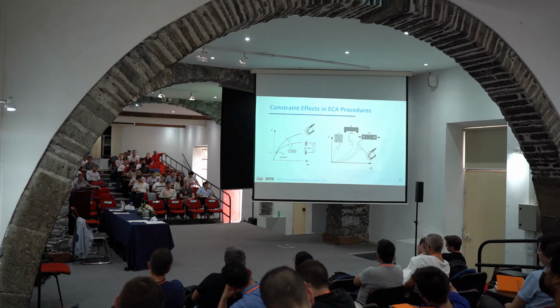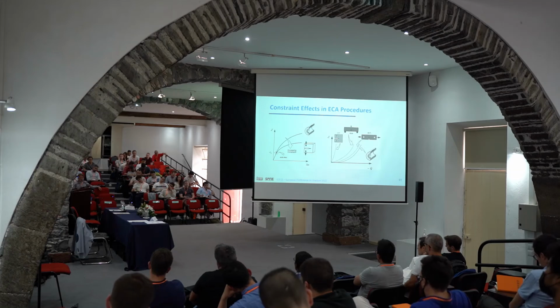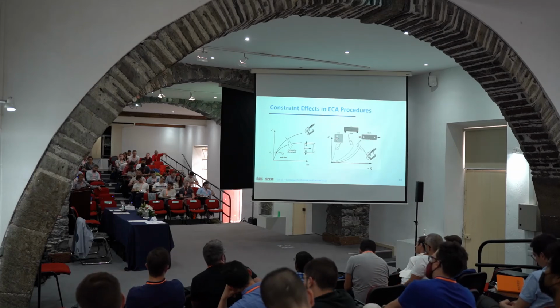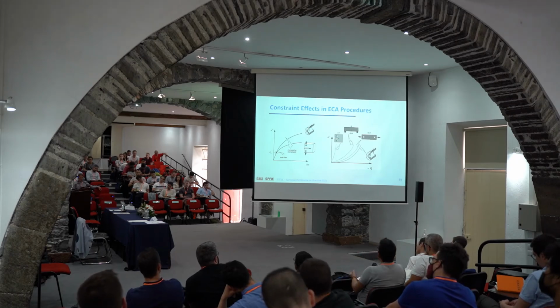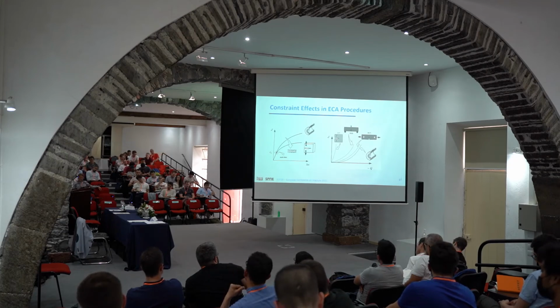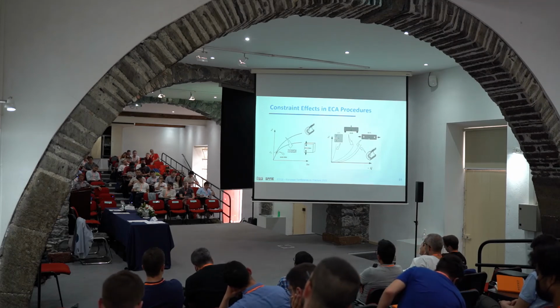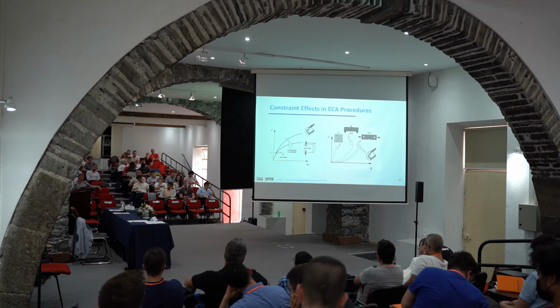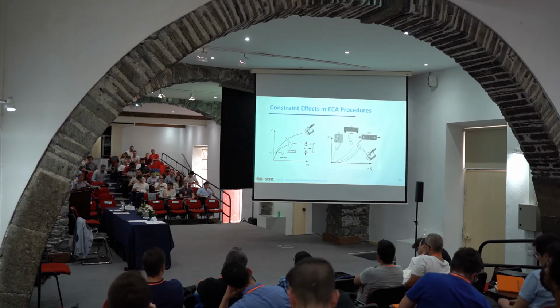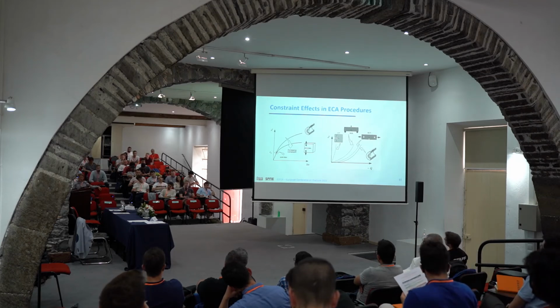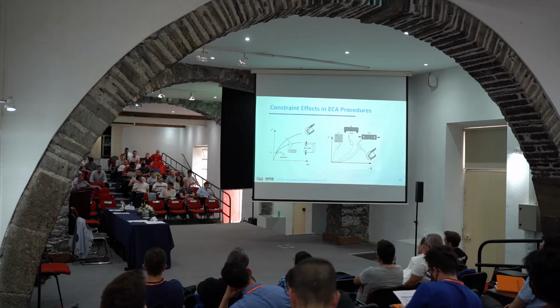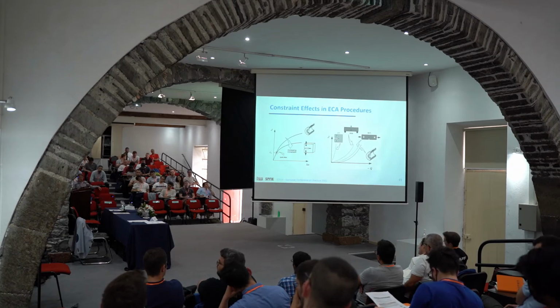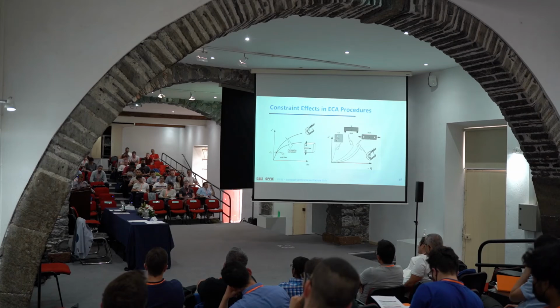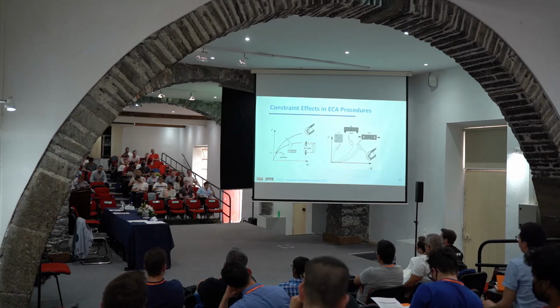And when the plastic deformation spreads out larger than a certain amount, I'm going to show you, the correlation, okay, that's what single parameter is, a correlation between J and the stress fields. When you have more plasticity than that, this correlation breaks down. So J no longer describes the stress field. Therefore, I need a second parameter. It's a very nice area, by the way. This is called multi-parameter fracture mechanics. There are 3 or 4 second parameters, but